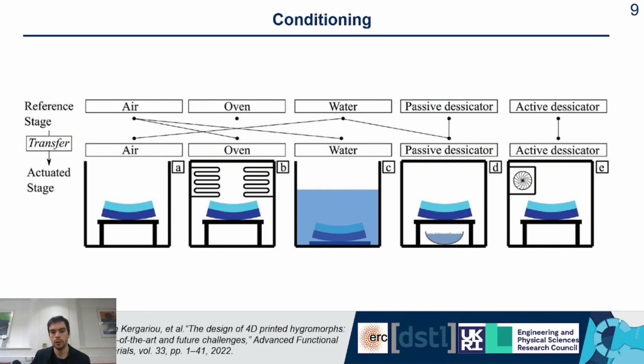The two most common are air to water and water to air, because it's very straightforward and you get a large actuation, so you understand the capability of actuation of your material. But you only have one value of actuation available, and it's fairly difficult to repeat because the temperature is difficult to control, and the temperature is always related to the humidity. And so you need to control both if you want to have perfect control of your actuation.